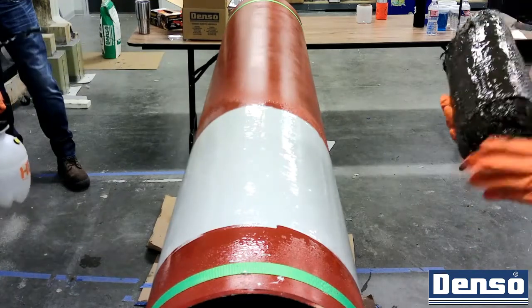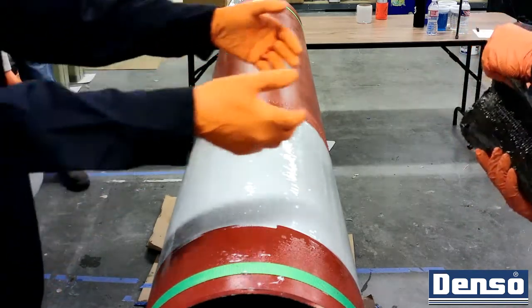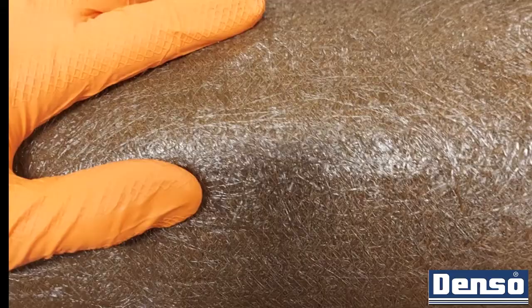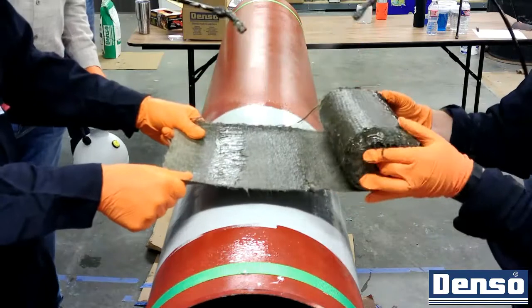Begin wrapping the bore wrap 1 inch from the edge of the epoxy primer. Ensure that you are wrapping with the omnidirectional matting surface facing out, as we call it, chop on top. The woven side of the fiber, which looks like a checkerboard, is to be placed facing the surface of the pipe.